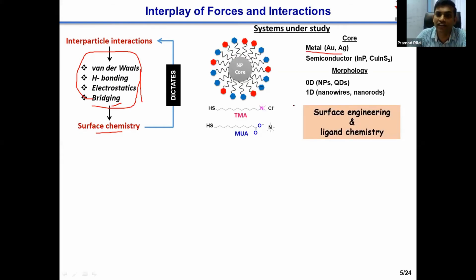We work with a series of nanomaterials, from metallic to semiconductor to magnetic, of different morphologies. Depending on our application or our studies, we choose a particular nanoparticle. For example, if we are interested in the plasmonic property, we go with metal nanoparticles. And if we are interested in the luminescence property, we go with semiconductor particles and so on. Once we decide which nanoparticle we want to work with, our next challenge is to functionalize a ligand of our choice without compromising the inherent properties of the nanoparticle. And this is extremely challenging, especially in the case of the luminescence property. Very often people see that when they functionalize a ligand of their choice, they lose the inherent property of the nanoparticle.